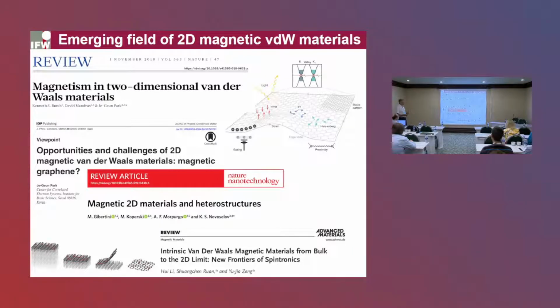And the reason for that is that these are van der Waals materials, which means they're easily cleavable, and one can, with not so much effort, achieve single or few layer two-dimensional magnetic systems, which is very flexible in terms of changing its properties. For instance, depending on the chemical composition or some external stimulus, like strain or pressure, one can change the spin Hamiltonian from a truly isotropic Heisenberg spin Hamiltonian to an Ising one or to an XY one. One, in principle, can think of doping of these two-dimensional layers by electrical gating. And that provides many possible and really interesting functionalities of this system. And there were a lot of very influential articles in the recent literature on that point.